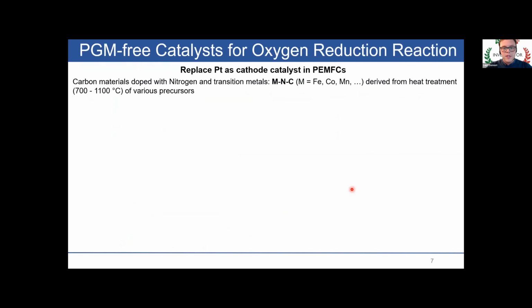from these sensitive countries. I would like to start to describe a little bit my work, starting with my work on the development and testing of PGM-free catalysts for oxygen reduction reactions, with the application on the cathode of proton exchange membrane fuel cells as a replacement for platinum. These materials are carbon-based materials which are doped with nitrogen and transition metals like iron, cobalt, or manganese, and are synthesized after a heat treatment at high temperature.